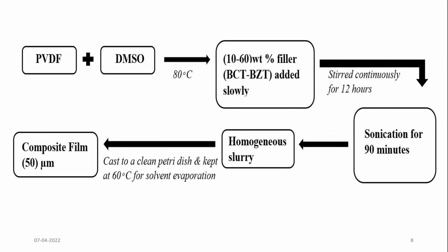Then the PVDF was mixed with DMSO and heated at a temperature of 80 degrees Celsius. When the pellet of PVDF was completely melted, BCT-BZT nanofiller was added slowly with different weight percent from 10 to 60. Then it was stirred continuously for 12 hours, then sonicated for 90 minutes for mixing. Then a homogeneous slurry was prepared, which was cast to a clean petri dish kept at 60 degrees Celsius for solvent evaporation. A composite film of around 50 micrometer thickness was generated.